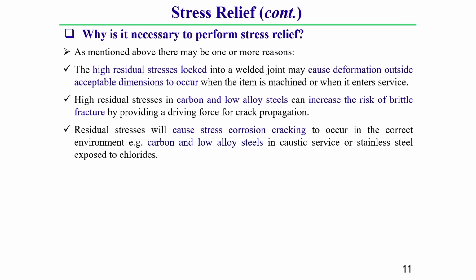Okay. Now, why is this stress relief operation required? I am discussing it in a little bit of detail here. First of all, we know that the high residual stress locked into a weld joint may cause deformation outside acceptable dimension when the item is machined or when it enters service. So, stress relief operation is required to minimize this residual stress, because once we machine that component or use it in service condition, due to this residual stress some deformation can occur outside the acceptable dimension. This you should keep in mind.